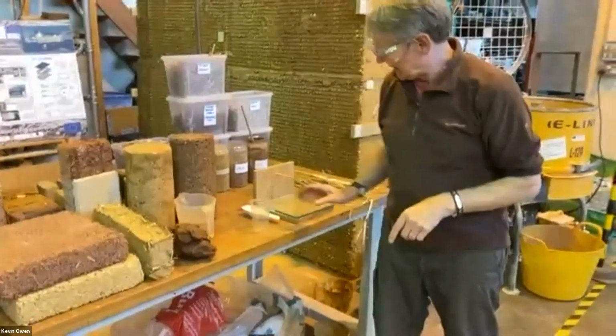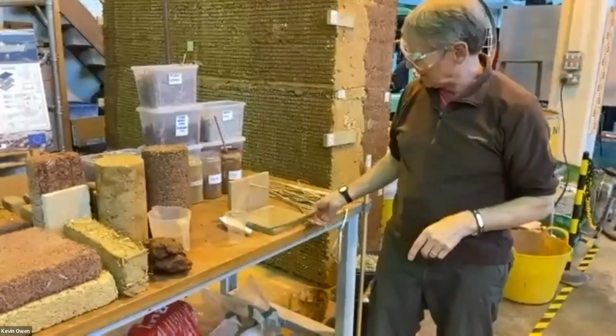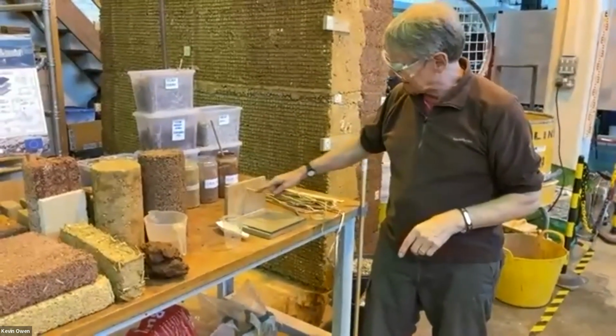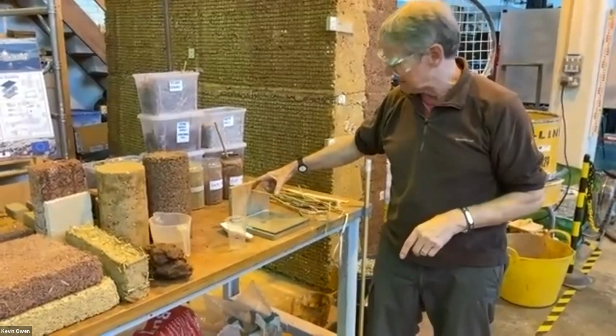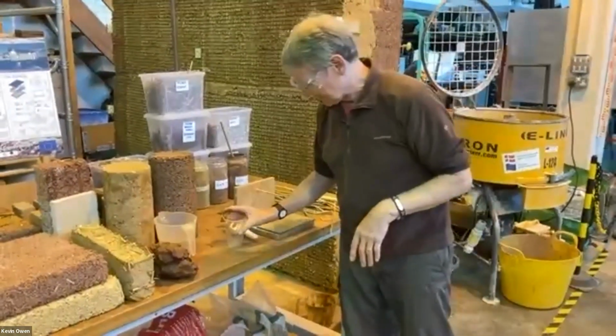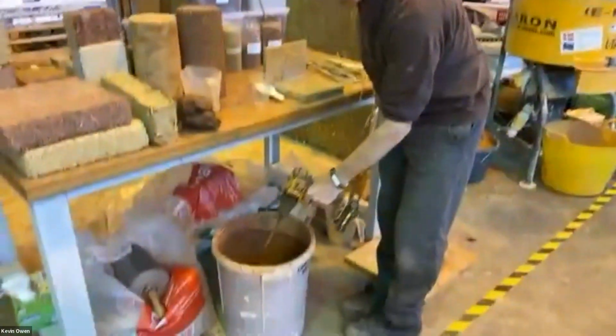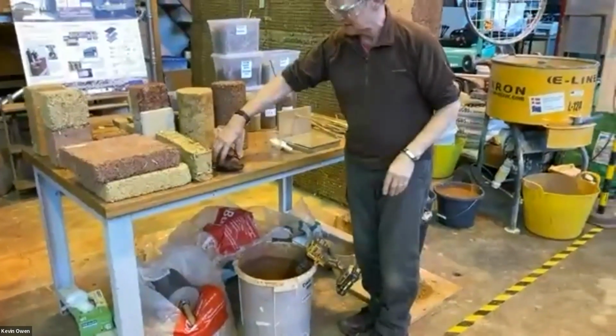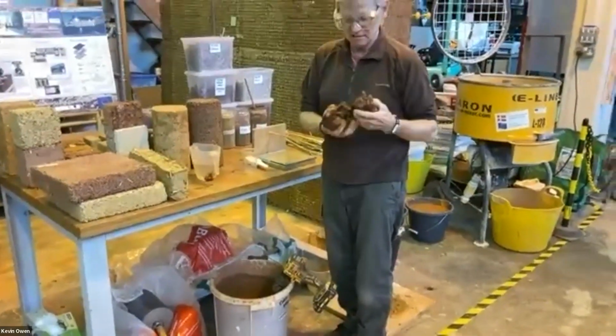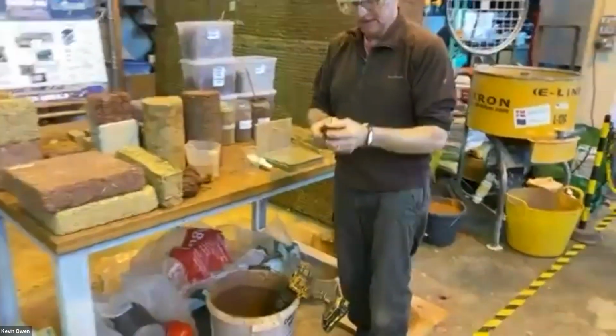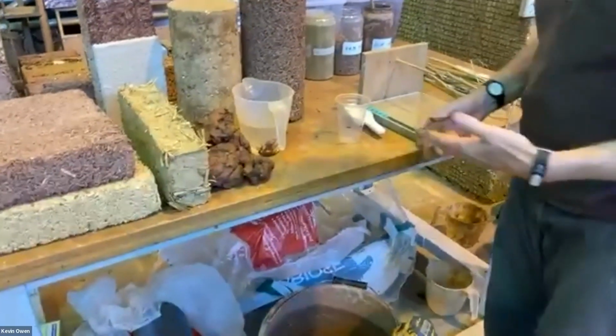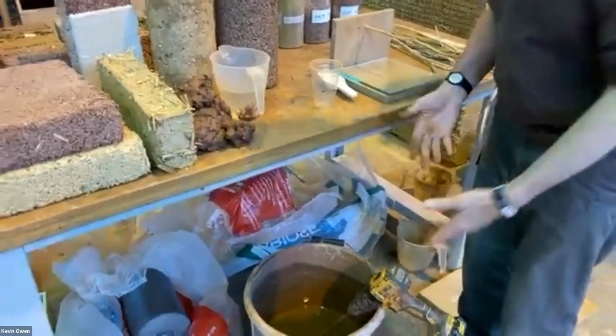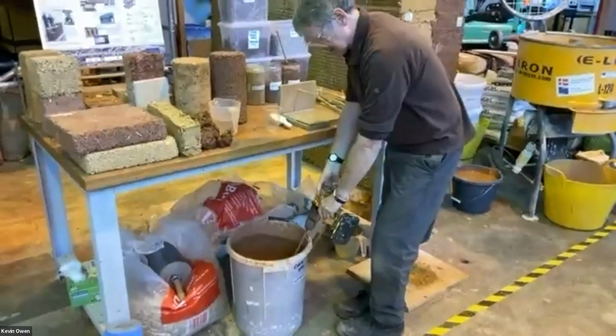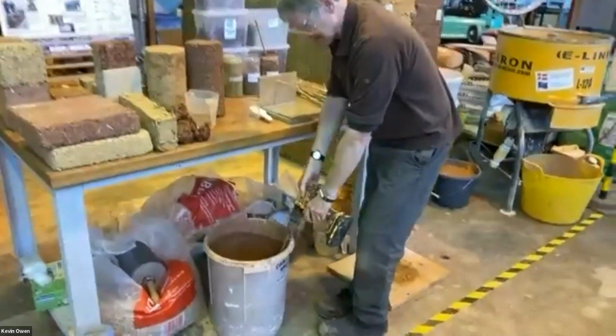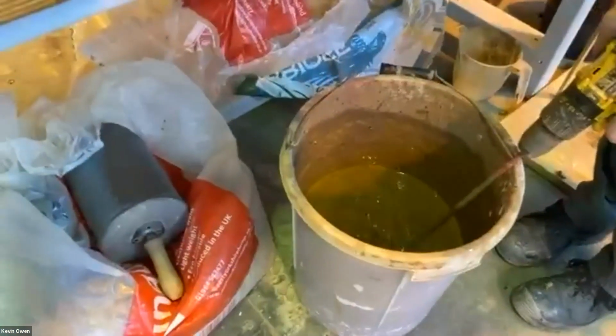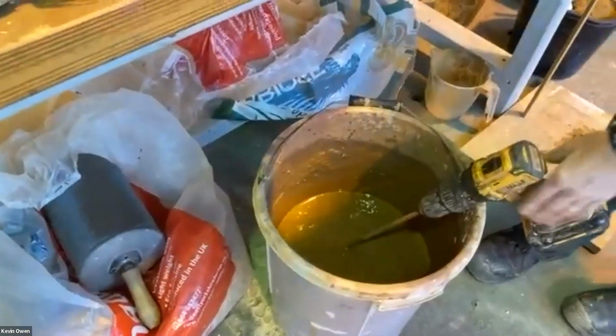and a little frame here that I've got on a piece of glass with a little peg sticking out there, and that is 100 millimetres, so 100 and 100. And then down here we've got some of our slip. The slip is high clay content, a local clay, not too far away from Plymouth. Very high clay content, and just add water. So you keep adding water to that and mixing it until you get to a fairly thick consistency, to the point where you can take a measurement.